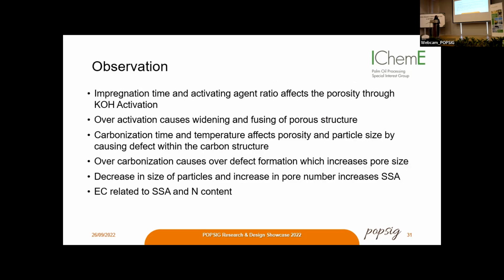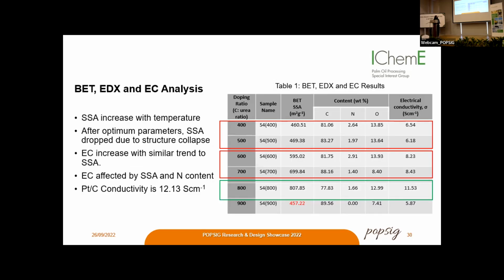So when we compare the electrical conductivity with the specific surface area and the nitrogen content at 400 and 500 degrees Celsius, the specific surface area increases slightly, but the nitrogen content drops, which causes the electrical conductivity to drop as well. As for 600 and 700 degrees, the specific surface area increases, but the nitrogen content drops as well. However, it causes the electrical conductivity to increase. So that means that EC is affected by both specific surface area and nitrogen content.